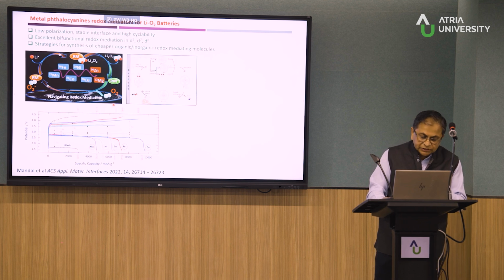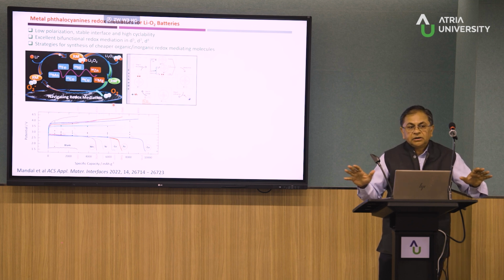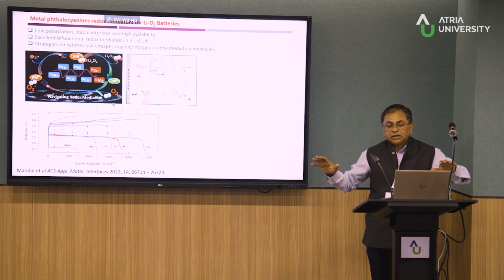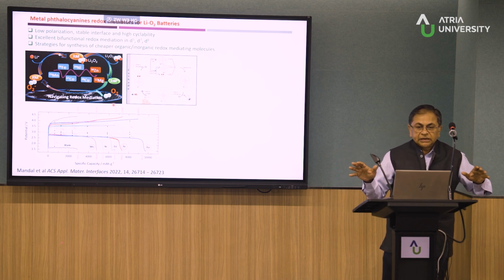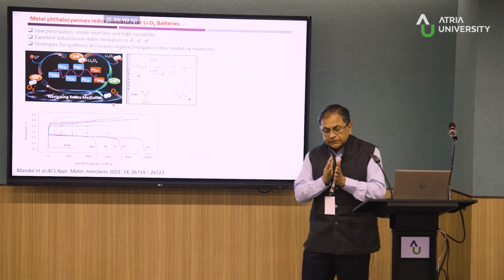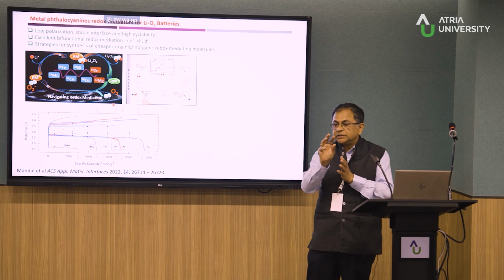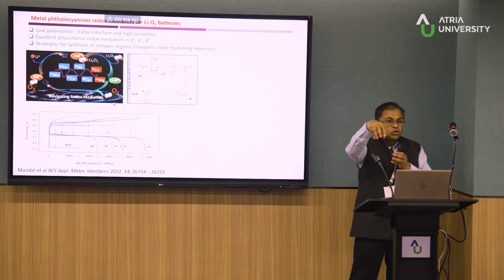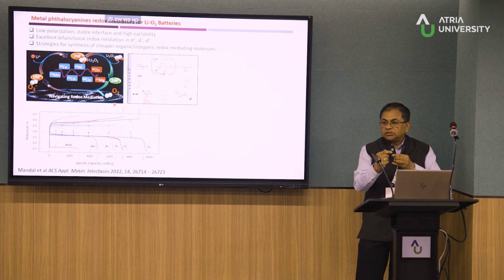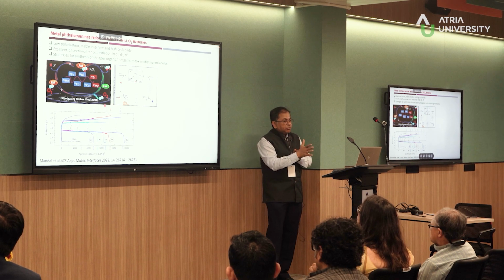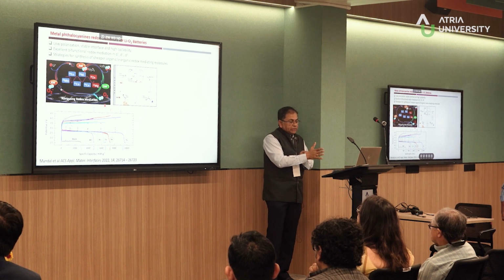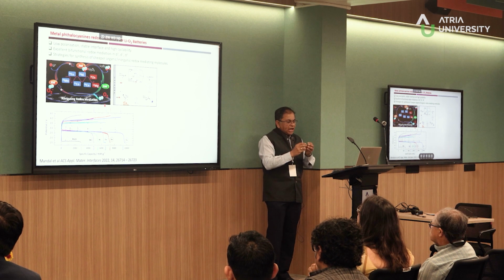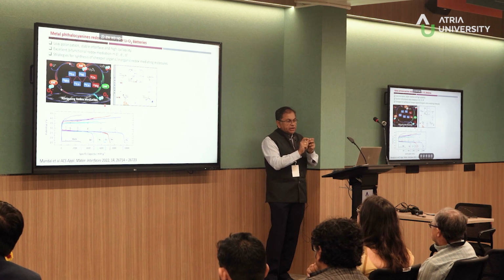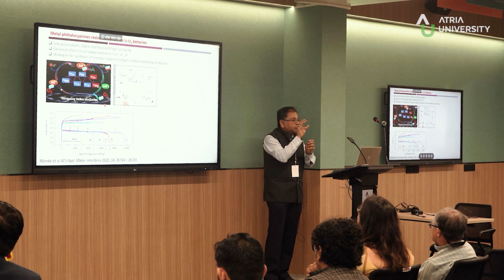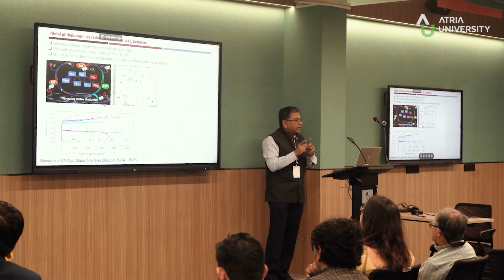For example, in the oxygen, this was done at least two years back, where we did an exhaustive study of the first-row transition metal phthalocyanines. So the idea here is that these oxygen cells use solid electrocatalysts, which are sitting on the gas diffusion layer. So what happens is, as you discharge the battery, firstly there is a problem with oxygen or any gas diffusion through the layer. But because of the irreversibility of the reaction, you start blocking the pores. Okay, so that's a big problem to carry on with electrochemistry.